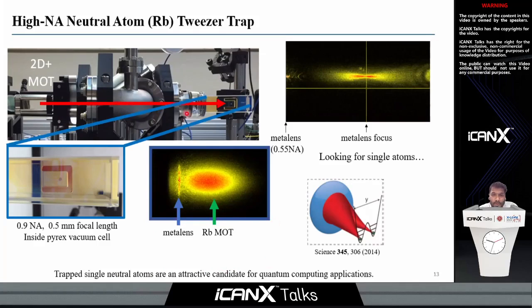So shown here is again the setup where we bring a two-dimensional rubidium MOT close to the metasurface focus, and in this particular case, instead of a low NA metasurface, this is a tweezer trap. So it's a high NA metasurface that is actually mounted inside the science cell. In this case, this particular metasurface is a 0.9 numerical aperture metalens. And here you can see the MOT close to the metasurface, and here is the lower NA 0.55 metasurface with the MOT slightly further away from it.